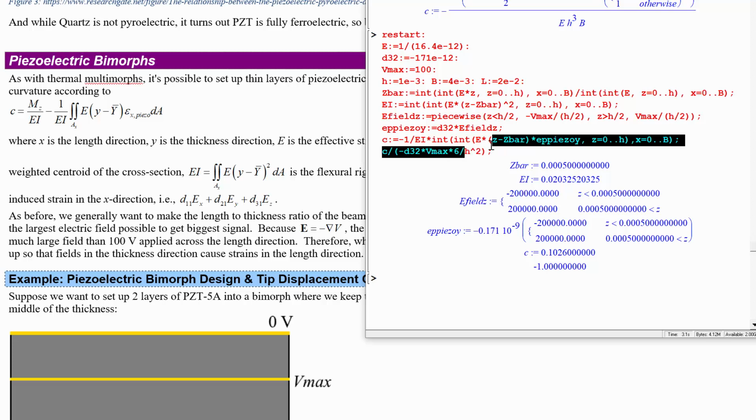The H shows up in there twice, and this scales twice as fast as you decrease the thickness. That said, the limit of the voltage you can apply also goes down as you make things thinner. The thinner it is, the less voltage it can take before the electric field gets to the breakdown field.